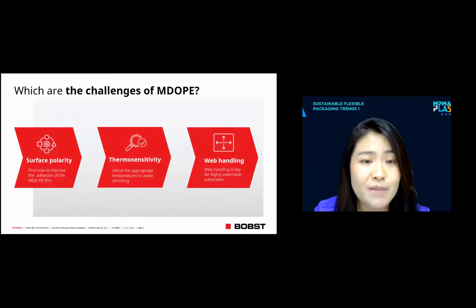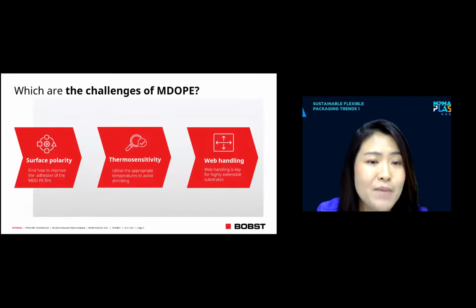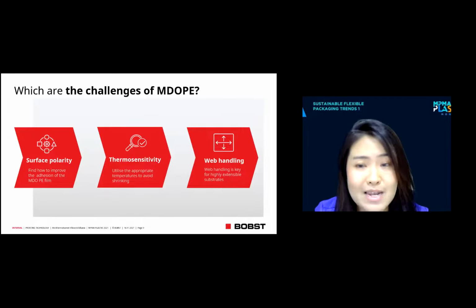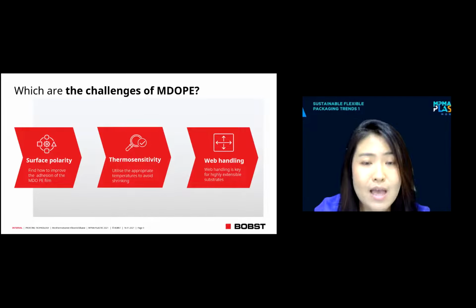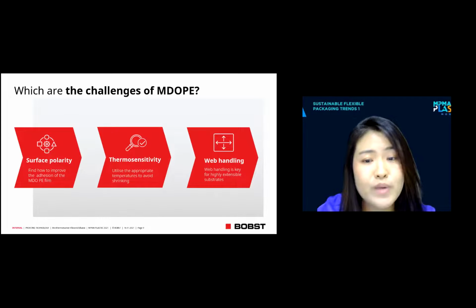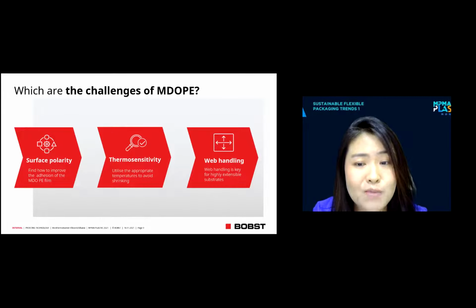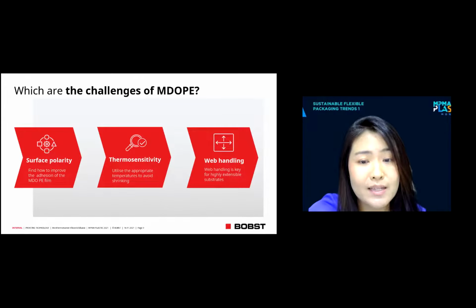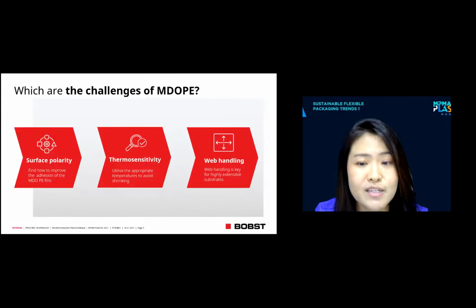The challenge of the MDOPE we found in 3 dimensions. First is the surface polarity. Secondly is the thermosensitivity. And the last one is web handling. How to improve the adhesion of the MDOPE? We found that during the coating phase, one challenge is the poor surface energy of the MDOPE, which has low polarity. The dyne level of the MDOPE is around 40.